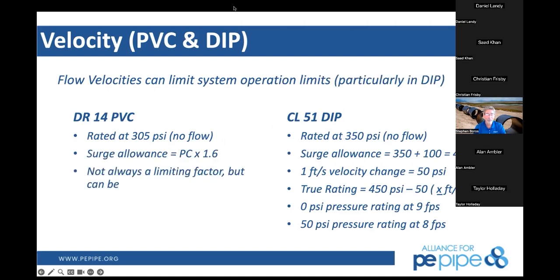So just to summarize a little bit, for instance, flow velocities and pressure ratings. For a DR14 PVC pipe, it has a pressure class of 305 and a surge allowance of pressure class times 1.6. Now that's for occasional surges, not recurring surges. It's 0 above that for recurring surges. For ductile iron, or class 51 ductile iron pipe, it's rated at 350 PSI, but that's for no flow. If you have any flow through it, 1 foot per second can result in a 50 PSI increase in pressure. And so at, for instance, 9 feet per second, you have no pressure rating left. It's all taken by the surge. So you have to design for that appropriately and mitigate it.